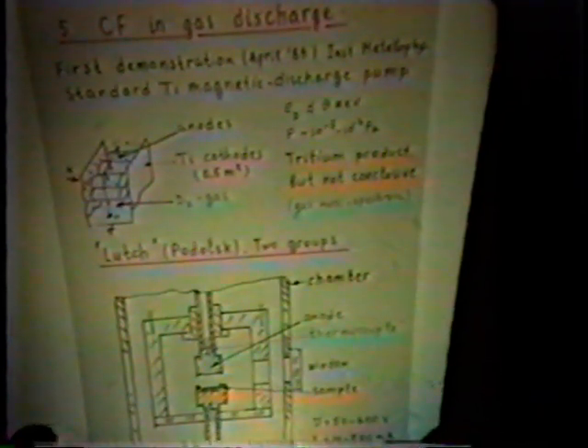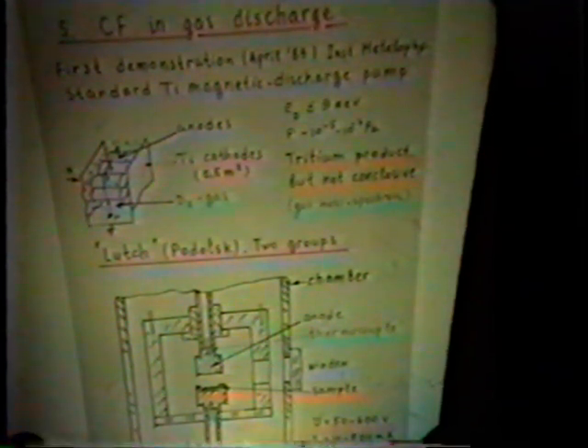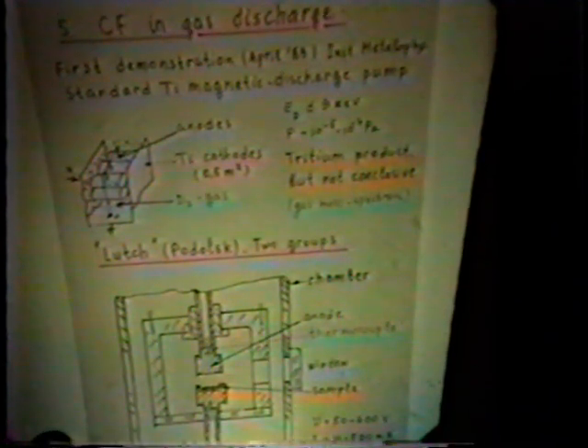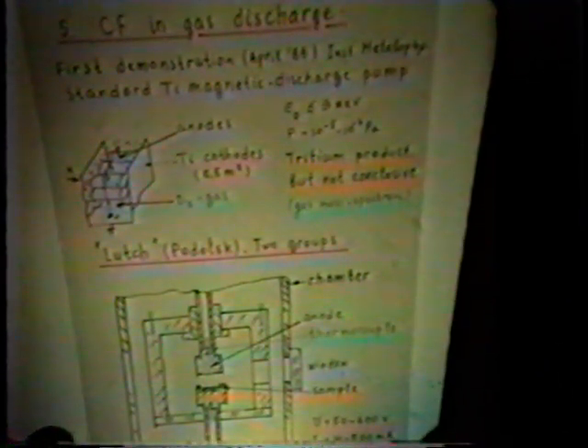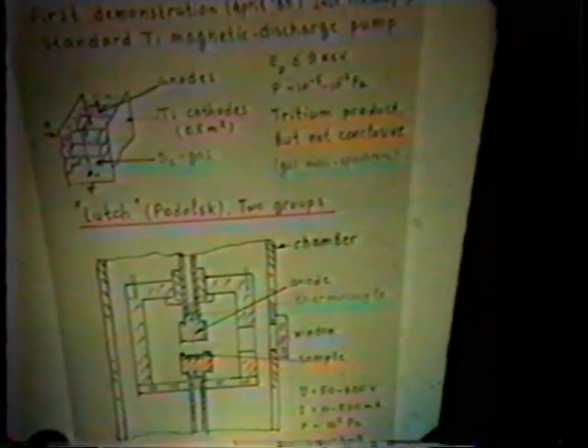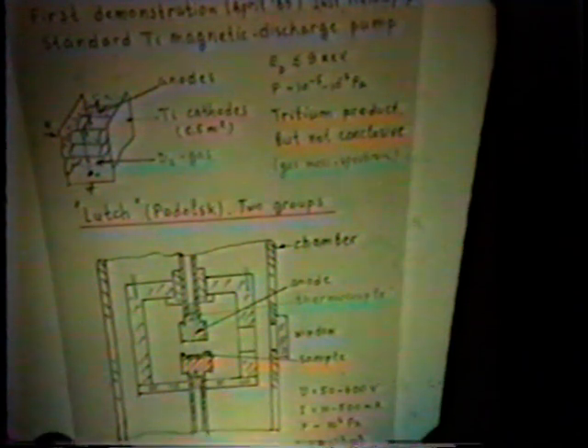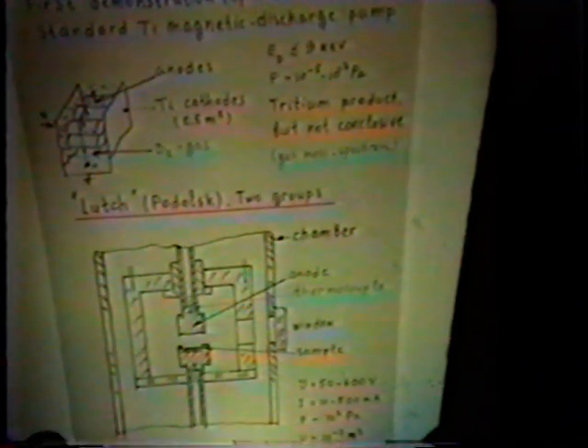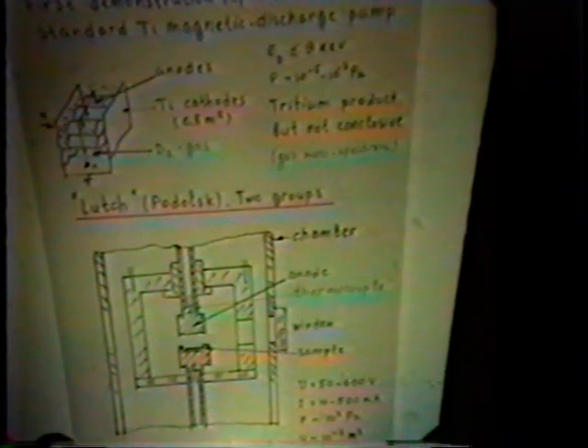The next topic is gas discharge experiments. The possibility of utilization of gas discharge for loading of metals in cold fusion experiments was demonstrated in early work which was done by a group from the Institute of Metallophysics of the Academy of Science. They used a standard titanium magnetic discharge pump, and they saturated with deuterium a large surface of titanium cathode, about half a square meter. And after a few hours of running, they observed evidence of tritium production. However, this first experiment was not conclusive quantitatively.